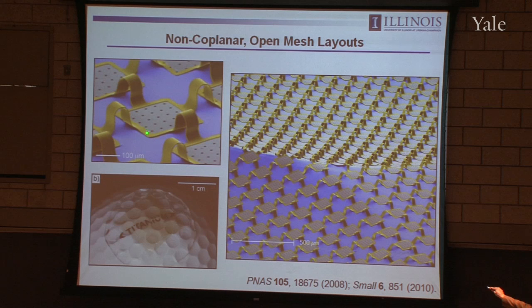It's an array of silicon nanomembrane islands connected by polymer metal interconnect bridges that adopt this kind of non-coplanar arc-shaped design. So the entire system is in an open mesh. The nodes of the mesh correspond to silicon, where you can imagine populating those regions with devices. And then the interconnects in the mesh are not bonded strongly to the underlying elastomer.